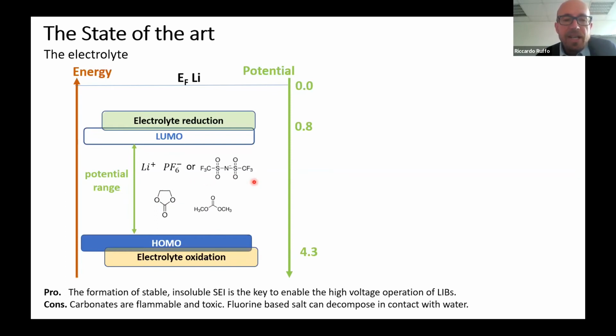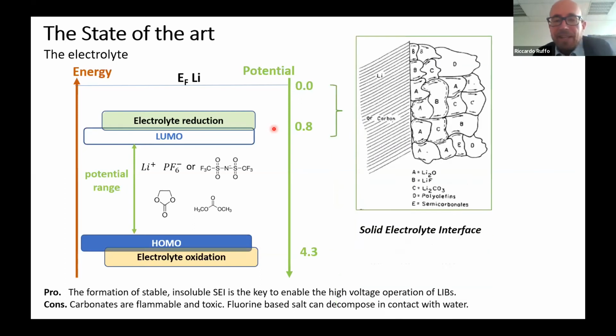This combination of chemicals has very good stability towards oxidation, but they pay a little bit in terms of reduction. So basically, they cannot be operated below 0.8 volt versus lithium, but we know that our batteries are working at more than 4 volt. So the key aspect here is the formation of what we call the solid electrolyte interface, which is a passivation layer formed during the first charge at the negative electrode.